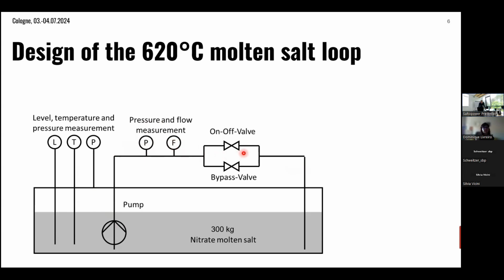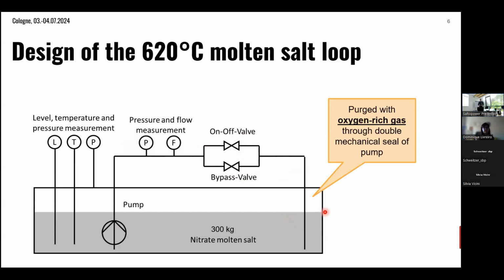We have flow measurements, and we operate it with two valves. One is used as an on-off valve, and the other one is used as a bypass valve. Also, we purge this oven with oxygen-rich gas to prevent the salt degradation, and this is done through the double mechanical seals of the pump. Also, for a few tests, we need to evacuate the system or reduce the pressure. So we have a vacuum pump, which we can actively control with a valve.